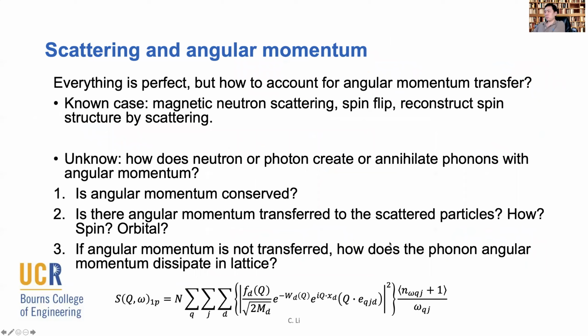I'm going to skip this. This is basically what the existing inelastic X-ray scattering theory does. The key part is this term, which is a dot product of the photon wave vector change, which is a big Q, and this E here, which is the phonon eigenvector. As you can easily tell, there is no part of this dynamic structure factor that takes into consideration the polarization of the photons in this process. So that's actually not considered.